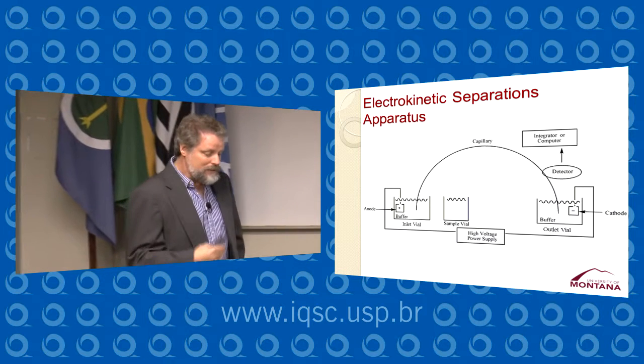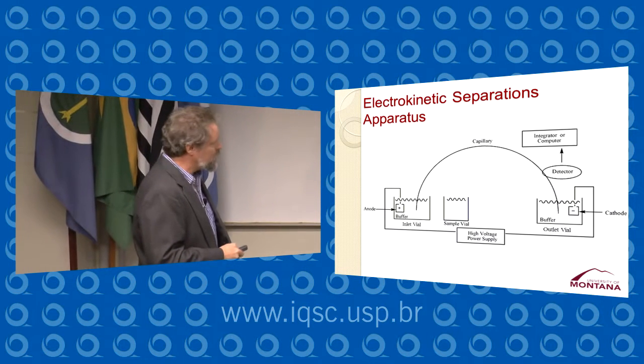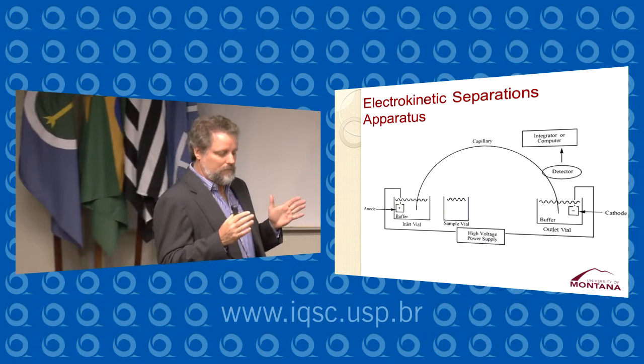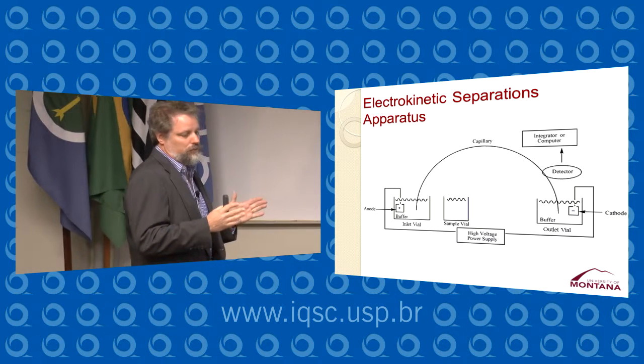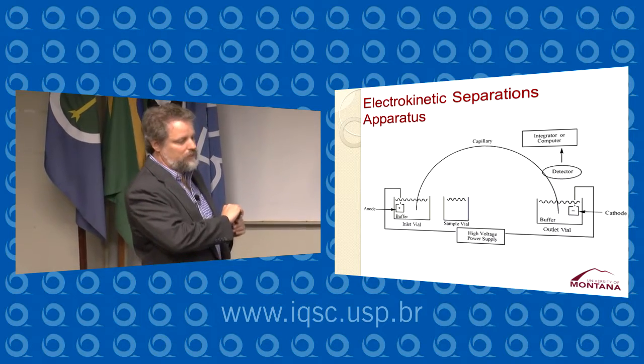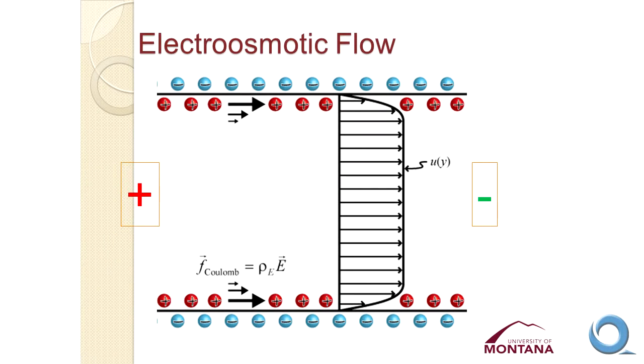So one of the things that's happening inside this capillary that may not be immediately obvious is that when we apply the electrical potential, we get a bulk flow, a flow of the buffer solution from the inlet end toward the outlet end, from the anodic end toward the cathodic end of the capillary. And that flow is generated by the fact that the fused silica capillary has a permanent negative charge attached to the capillary, and that's balanced by loosely bound cations close to the wall.